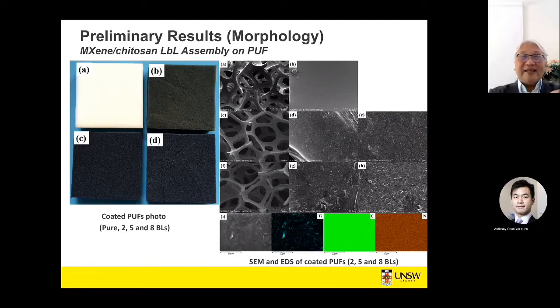If you look at the material before being layered with chitosan and titanium carbide, this is the pure material, and after 8 layers, you can see that it has darkened quite significantly because it is now filled with a lot of the titanium carbide. And these SEM images demonstrate the degree of material being deposited onto the foam.